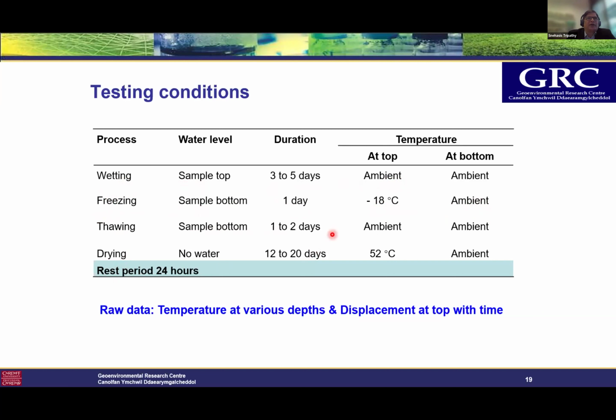Thawing occurred at ambient temperature. It took about 1 to 2 days. Drying, no water was supplied, and it took about 12 to 20 days for different materials. And the temperature at the top of the soil sample was 52 degrees centigrade plus. And at the bottom, it was ambient.